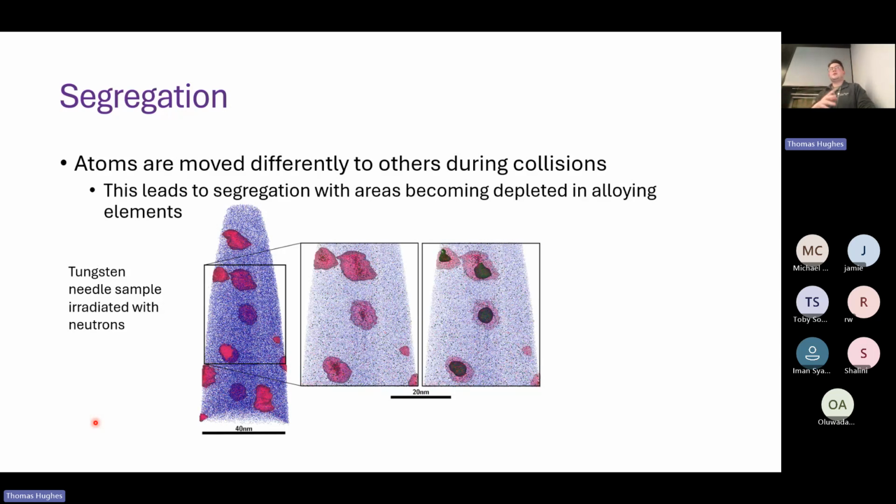So this is atom probe tomography. This is basically like a needle that they've irradiated, and then they can ablate the surface of it and then detect it. Almost like a mass spectrometer, but not quite. It's a lot more complicated, but this is how you can detect what your needle is made of. So we can actually see that even though our osmium and rhenium will have formed everywhere in our tungsten, it's actually congregated into sort of an osmium core with the rhenium surrounding it, sorry.